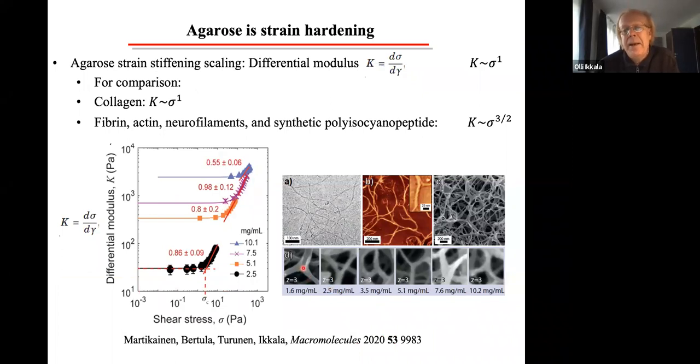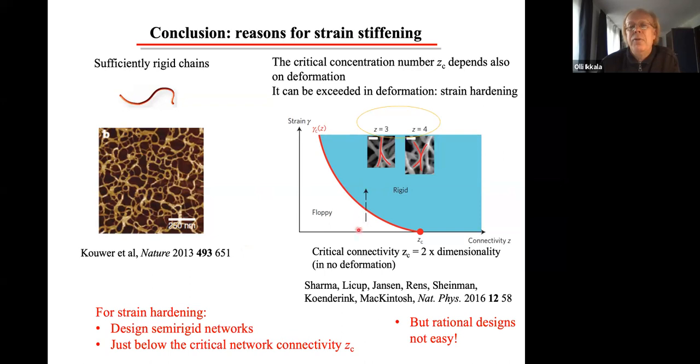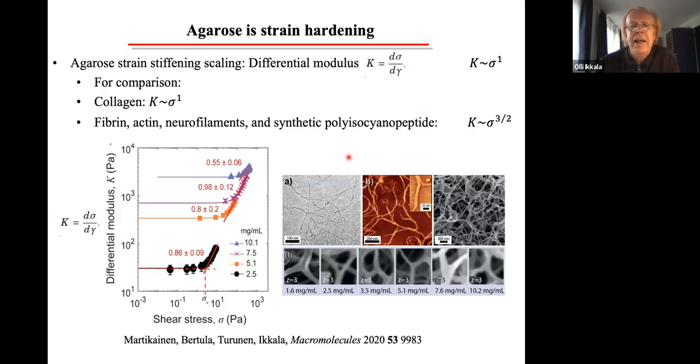And we saw in the microscopy that in all cases, the junction number was 3 before the shearing was starting. So it was exactly like I showed in the previous slides, that upon deformation, this material transformed to above, across the critical coordination number. You remember this. So we first have the coordination number 3, and in deformation, we pass over this border to this rigid value. So in principle, we can somewhat well understand now what happens in the system, but not extremely in depth. So it still requires quite a lot of physics.